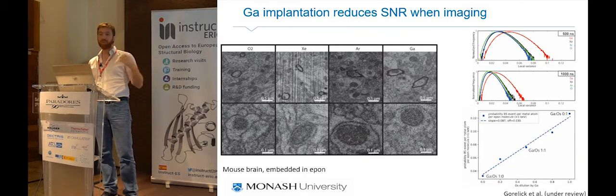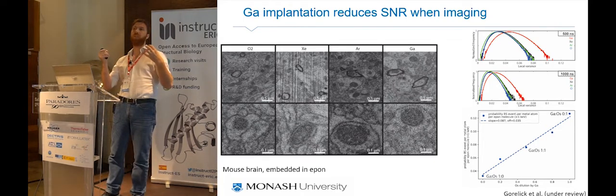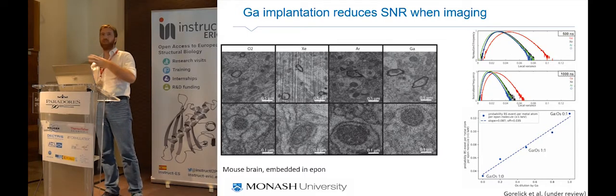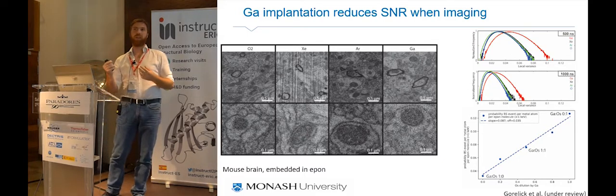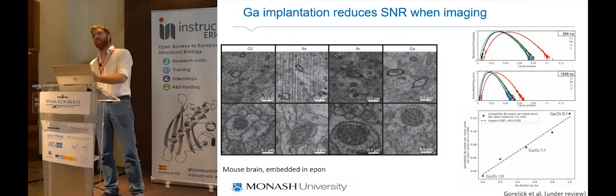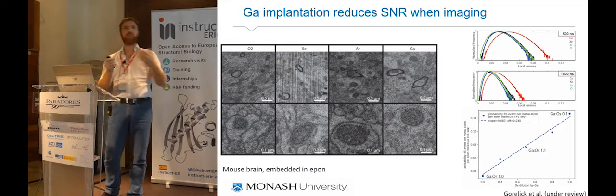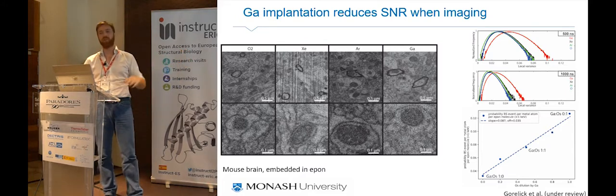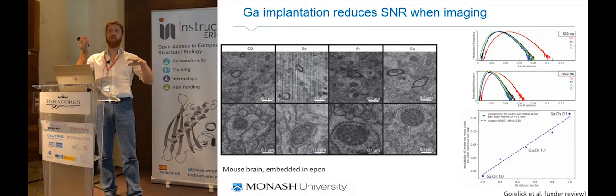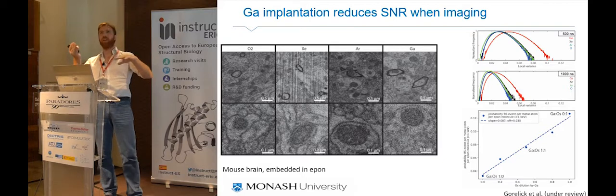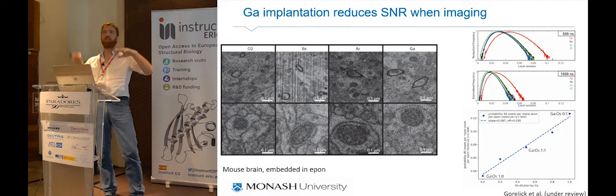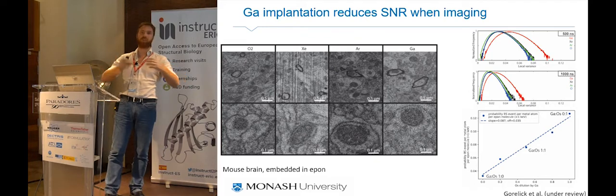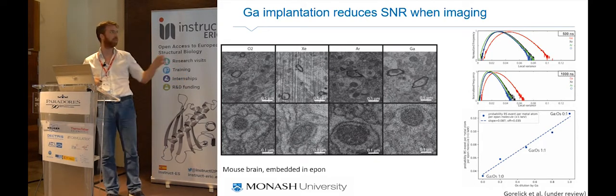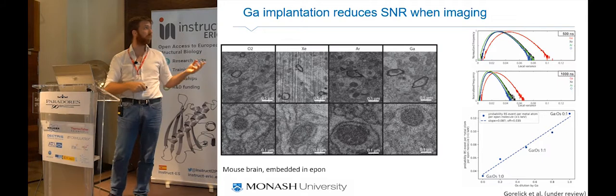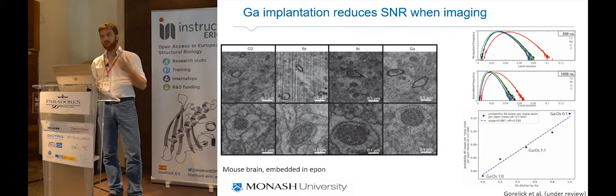So what happens is that you have gallium, which is a metal, it's heavy, but it's not as heavy as the osmium, and it's heavier than the resin, which is made mostly of carbon and nitrogen, so it's just in between. And implantation is a phenomenon which just happens randomly. So basically you are lowering the backscattering probability in areas which are osmicated, and you are increasing the backscattering probability in the background. So you're just turning your nice image, crispy staining, into a noisy face.